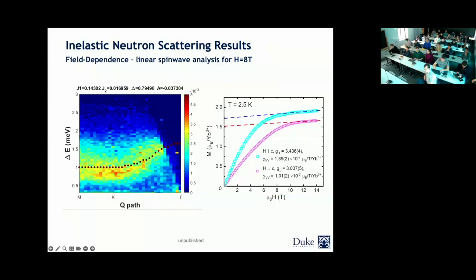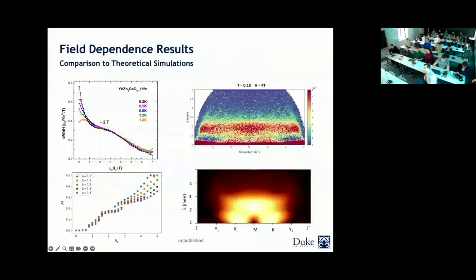This is an ongoing process, but I'm going to show you some very preliminary data, which was done by Joel's group. They started to look at J1, J2 for the Dirac quantum spin liquid as a function of different fields, for different anisotropy parameters, and they're able to get these plateau-like features at almost the same field. When they go to an intermediate field, they also see excitations at lower energies compared to this. But this is very preliminary, and we still need to work more on this to understand it better.